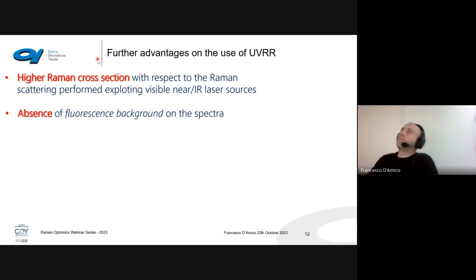There's a second important aspect. As people who work with organic samples, or for example archaeological samples and other kinds of samples, know, visible range spectra are always affected by a strong fluorescence background, which is emitted together with the Raman signal. Since the probability of fluorescence is much higher than the probability of Raman scattering, often we have visible spectra full of fluorescence. By moving to the ultraviolet, we can avoid this effect and have spectra free from the aforementioned fluorescence background.